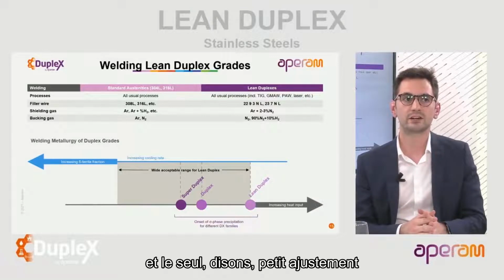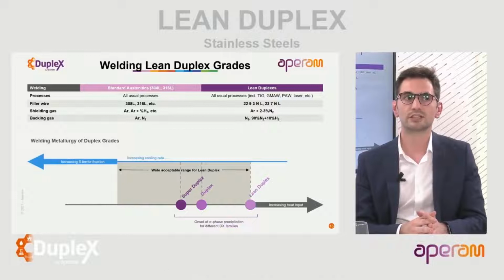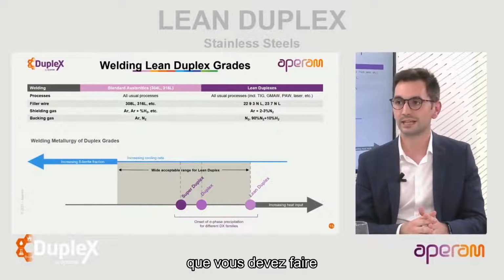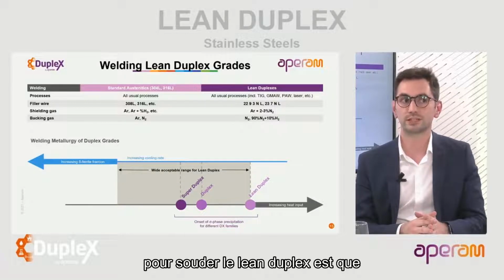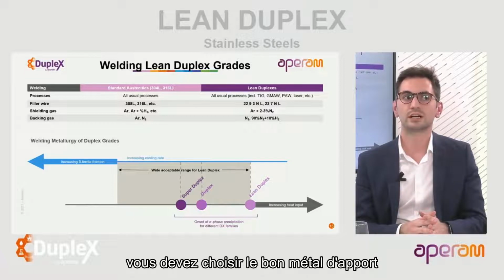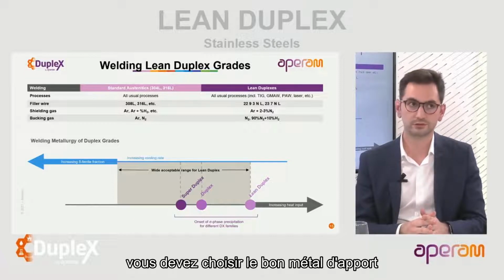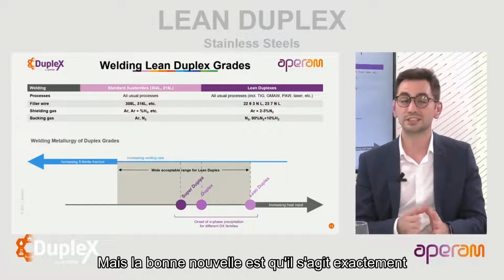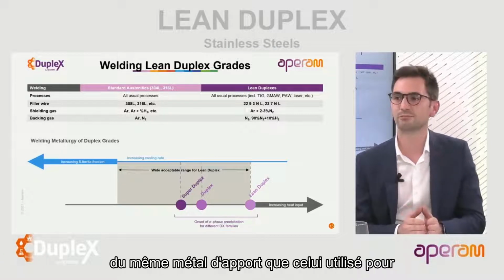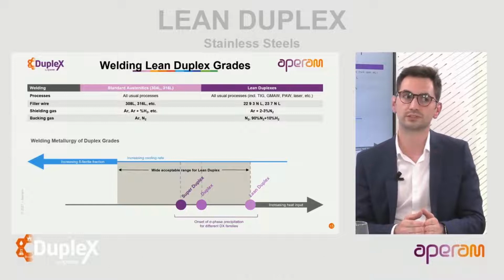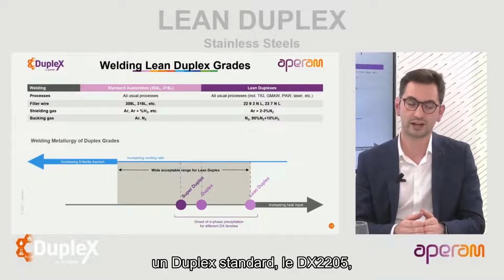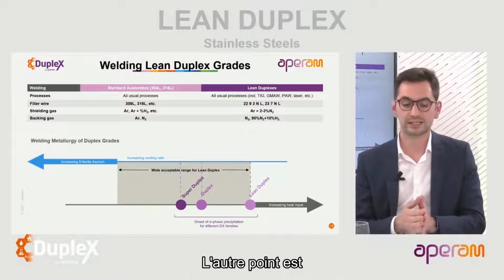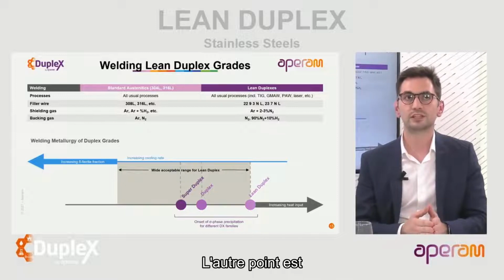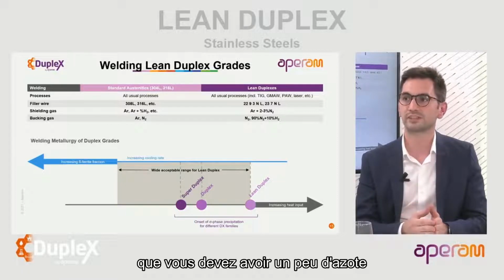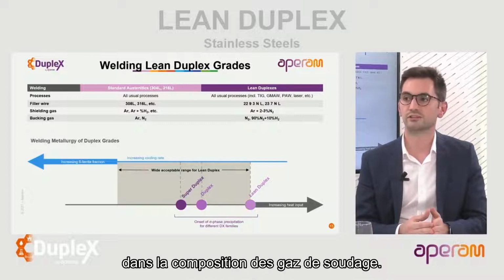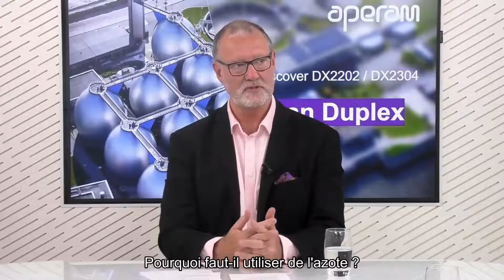And the only small adjustments that you have to make in order to weld Lean Duplex is that you have to choose the right filler metal for the welding. But the good news is that it's exactly the same filler metal that is used for a standard duplex, the X2205, which is widely available. And then the other point is that you have to have a little bit of nitrogen in the composition of the welding gases. Why should you use nitrogen?